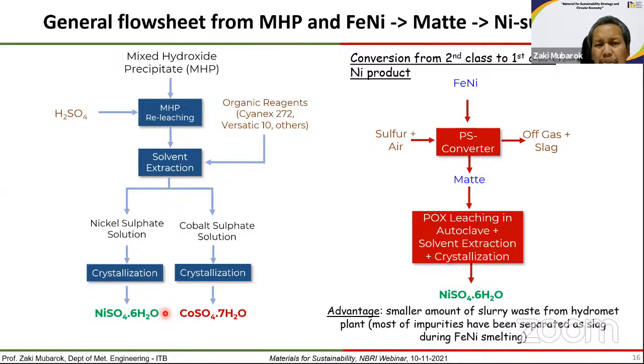And in addition to this route, there is also another route using saprolite ore, basically, or using existing facilities, or converting the second class of the product due to higher, increasing demand for battery. Then ferronickel or even nickel matte is converted to matte, nickel sulfide, by injecting sulfur here in Pierce-Smith converter, and this matte is dissolved in pressure oxidation leaching in autoclave, followed by solvent extraction, crystallization, similar to the route started from the ore, or from MHP.